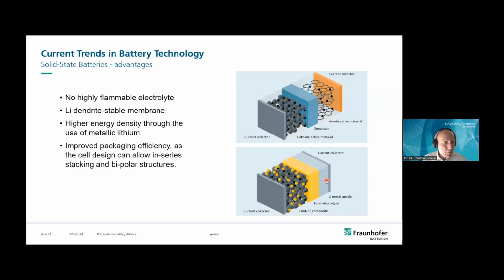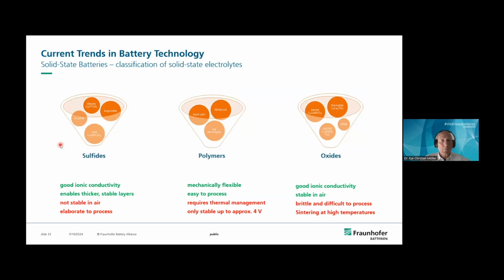What are the advantages of this technology? First of all, you have a non-flammable, non-liquid electrolyte. So the safety of the cells is better, and because you don't have a porous separator but a solid one, it should be possible to use a lithium metal anode, which is much thinner than the carbon anode active material electrode for the lithium-ion battery shown here on the top. So the energy density is the key driver for the cells, and the safety, and maybe some other smaller advantages.